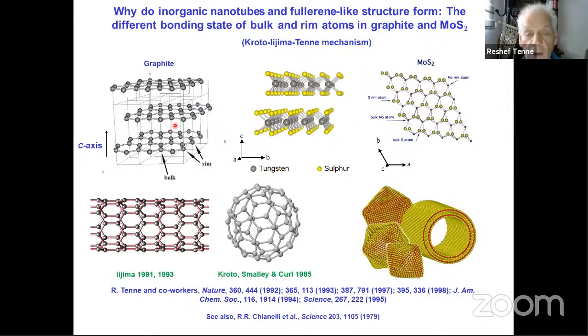But on the rim, they are only 2-fold bonded. If you make graphite small enough so that there are more atoms on the rim compared to the bulk, they will spontaneously fold. It pays them to fold and close into a structure like C60. This was 1985, and as you well know, the Nobel Prize went to them in 1996 or 1995, I don't recall. Then in 1991, Iijima proposed, actually it was already in the literature, but Iijima observed very nicely that these carbon nanostructures, or graphite nanostructures, are not stable, and they can form nanotubes. From that, the whole science of carbon nanotubes started in 1991.